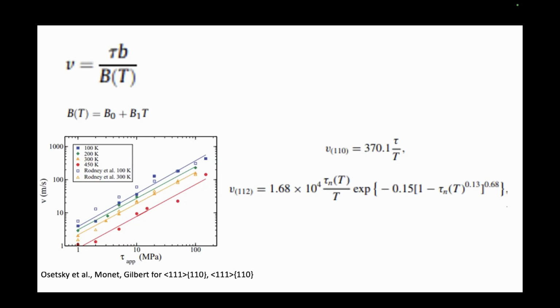In the literature, there are some studies that reveal the mobility law of both edge dislocation and screw dislocation, and these are the studies. Mostly, phonon drag is the main mechanism for edge dislocation, so there is no thermal activation. But screw dislocations are thermally activated. So for edge, like in FCC, it's straightforward. The mobility law for edge is just shear stress times the Burgers vector divided by the drag coefficient, and the drag coefficient is just a function of temperature. So this is just edge.